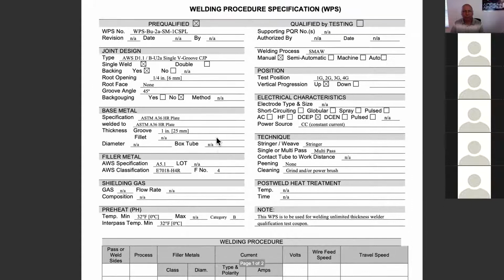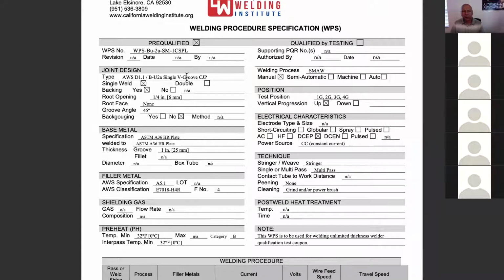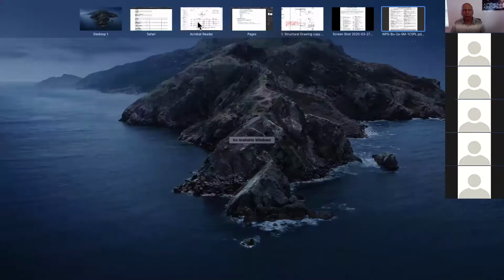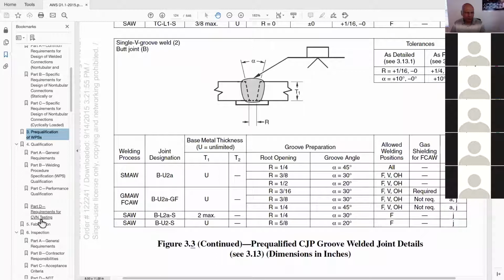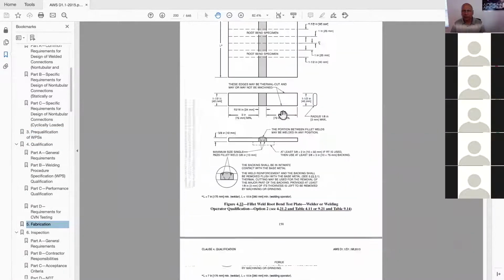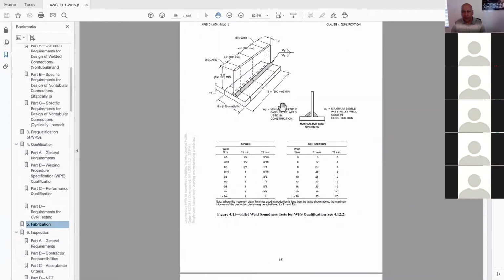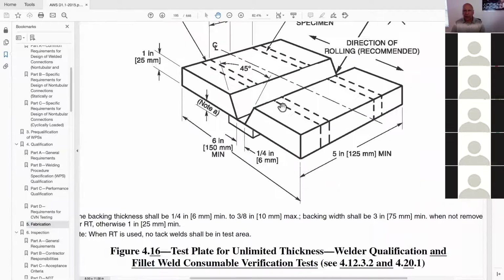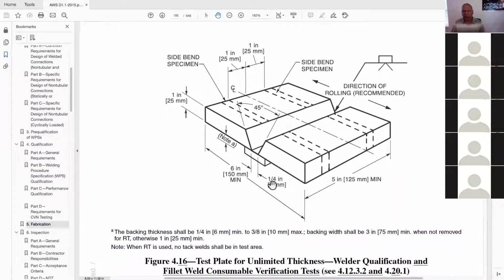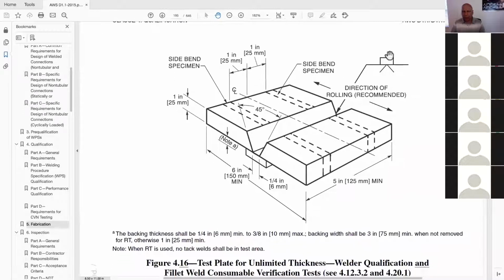All right, and so therefore in our WPS we specify that. It's a single V groove, complete joint penetration, single weld because it's welded from one side only, root opening 1/4 inch, root face none, it is beveled to a sharp edge, groove angle 45, and normally in a WPS you'll see a range. In this case we're not giving it a range simply because when we were looking at clause 4 and we went to the figures of clause 4 and we looked at the welder qualification test, it did not give us a range. It just simply said 1/4 inch root opening and then 45-degree groove angle.